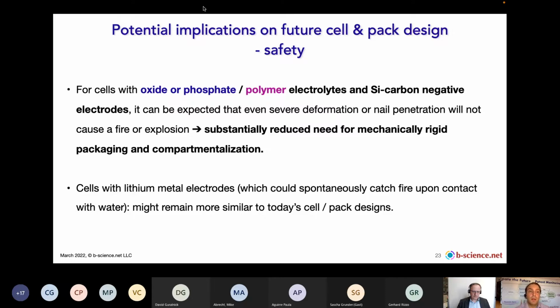So, for example, for cells with oxide or phosphate polymer electrolytes with silicon carbon negative electrodes, one can really expect that even severe deformation or nail penetration will not cause a fire or explosion, and so presumably that leads to a much reduced need for mechanically rigid packaging and compartmentalization.